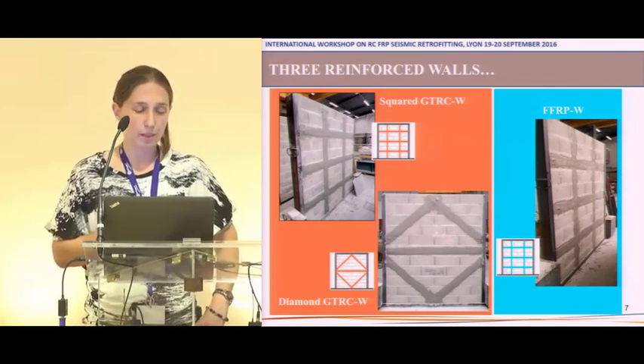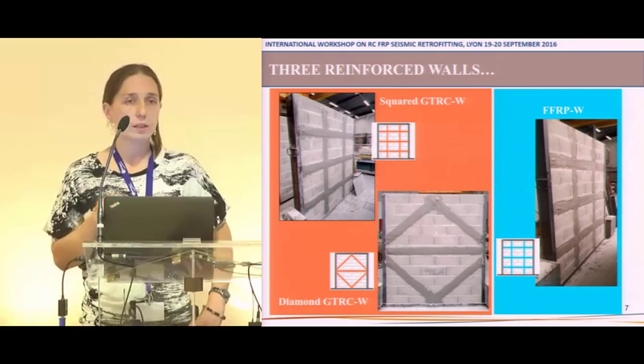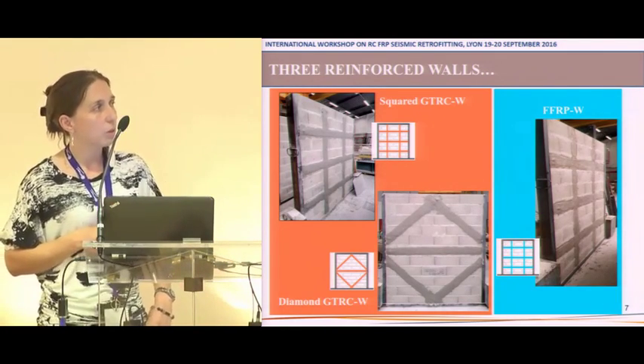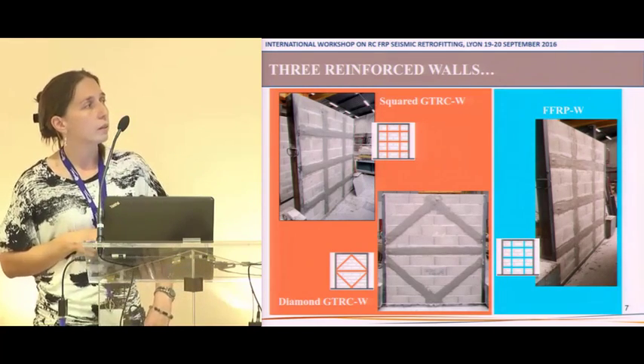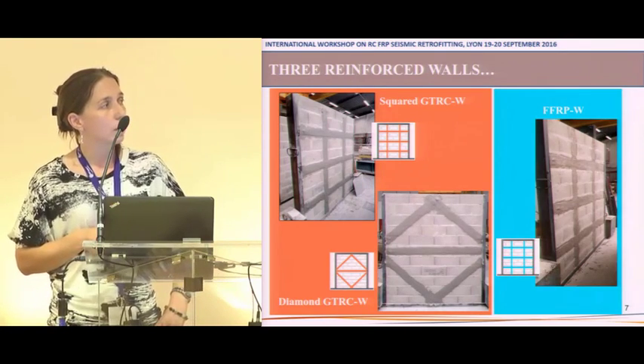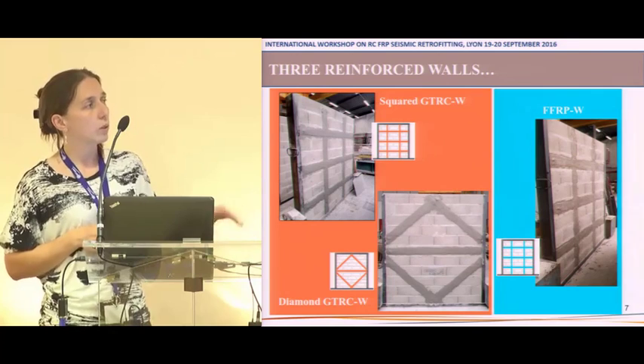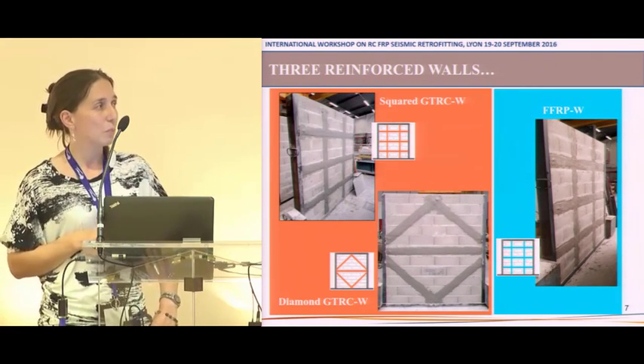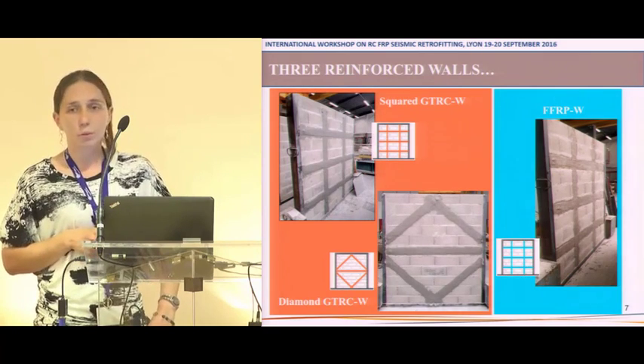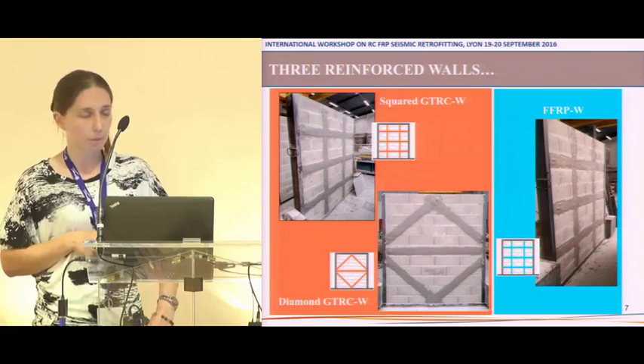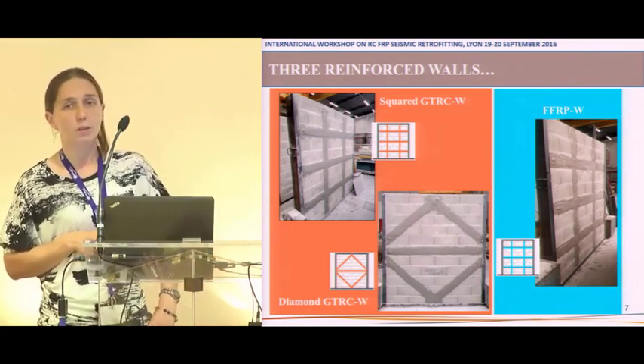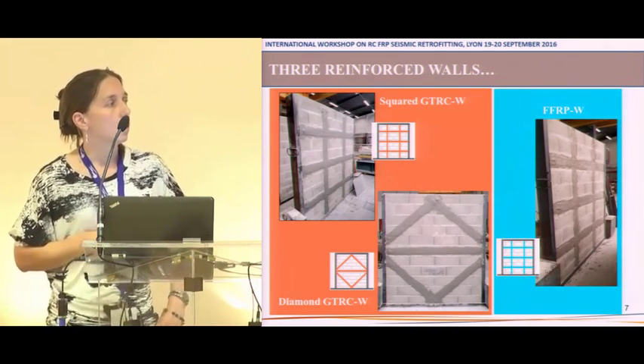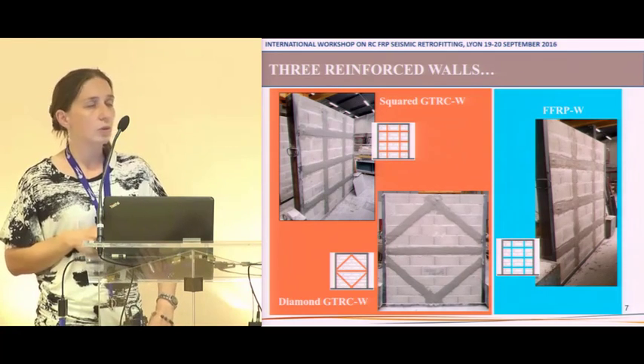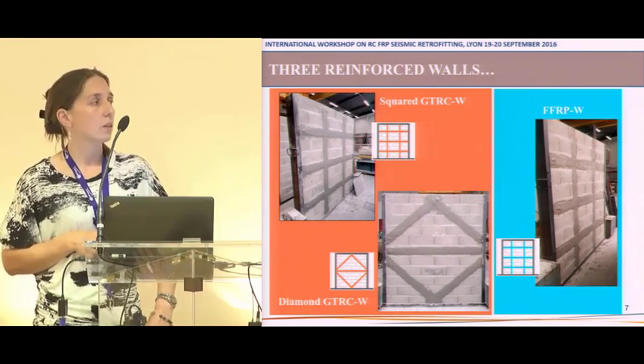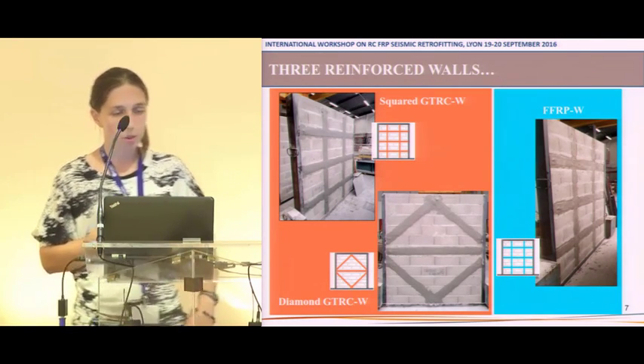3 reinforced walls have been tested, and for all the configurations, only the tensile face has been reinforced. In the first configuration, which is denoted squared configuration, 3 100 millimeter bands with a clear spacing of about 60 centimeters have been used in the horizontal direction, and 2 100 millimeter bands with a clear spacing of about 75 centimeters have been used in the vertical direction. The same configuration has been adopted for TRC and for FRP. Then, concerning the TRC, we have added a diamond-shaped configuration where composite bands have been located transversally to the potential failure line that we could expect with our boundary conditions.